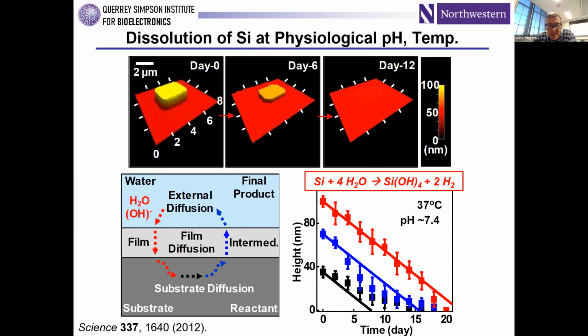It seems slow, but these are timescales that align very well with all sorts of medical applications for temporary implants. And the chemistry is shown here. It turns out to be pretty simple chemistry, very similar to that associated with bulk micromachining of silicon that's been going on in the MEMS community over the years, but typically done at very basic conditions. And here we are at a near neutral pH. It's still a chemical reaction that's at play. It just involves very, very low rate constants.